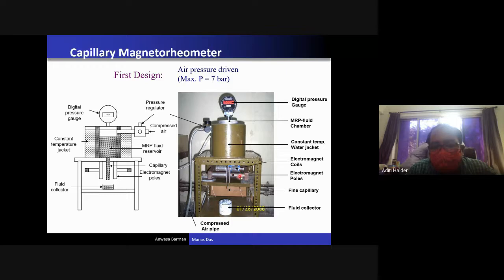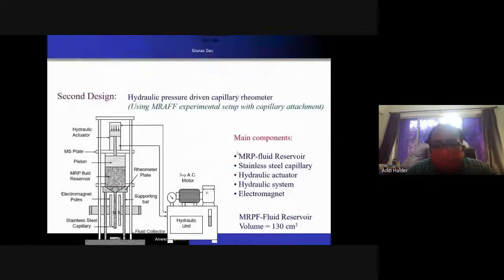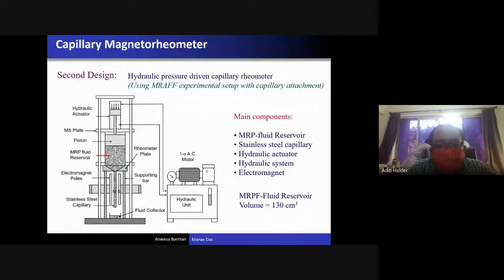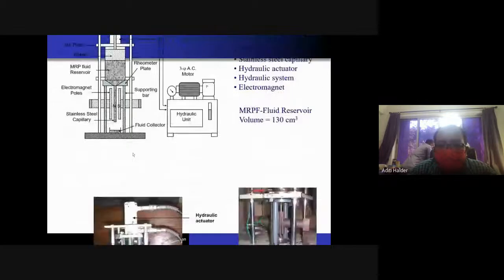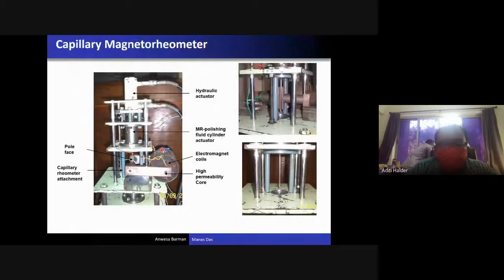Initially, this was the capillary rheometer, and this is the core material of the electromagnet. Through compressed air, this MR fluid was made to flow, but it did not work. Then we used the MR polishing experimental setup itself, the MRAFF experimental setup, as a capillary rheometer.